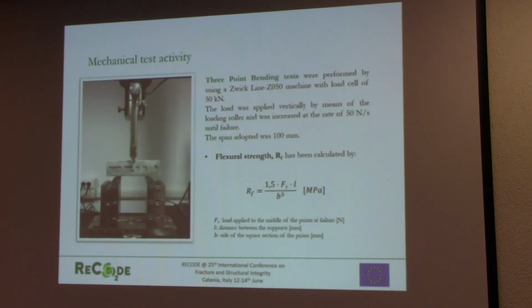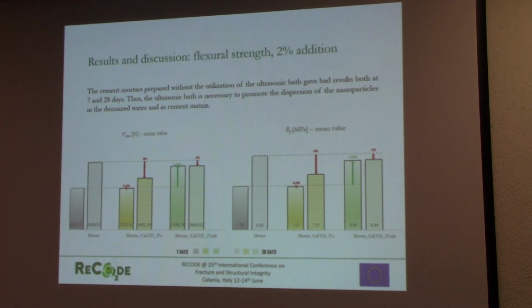The mechanical test activity was performed by means of the 3-point bending test and compressive test, by means of the testing machine with a load cell of 50 kilonewton. Regarding the first results, I report the histogram with the mean values, in this case, for the flexural strength, with the 2% addition of calcium carbonate nanoparticles.